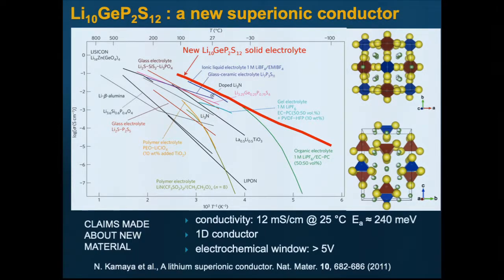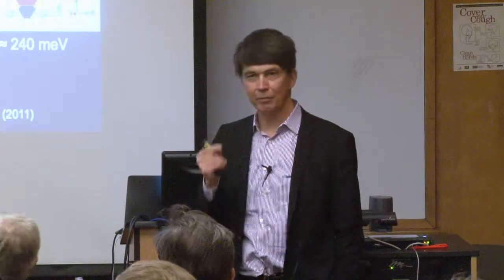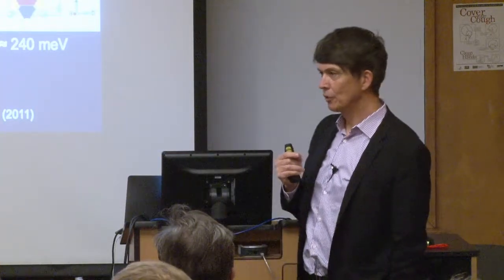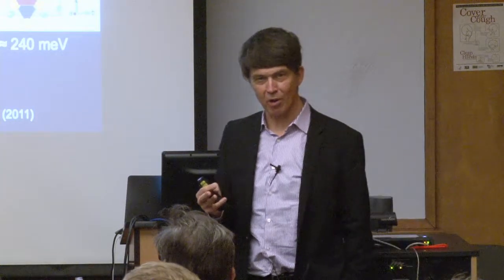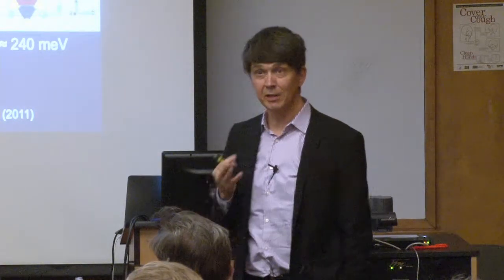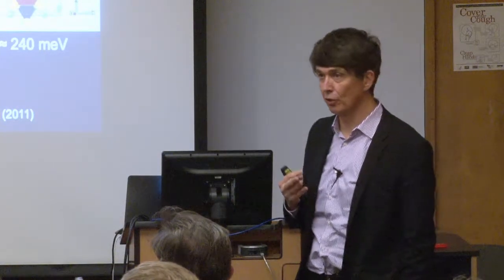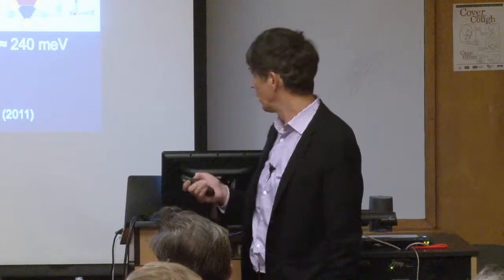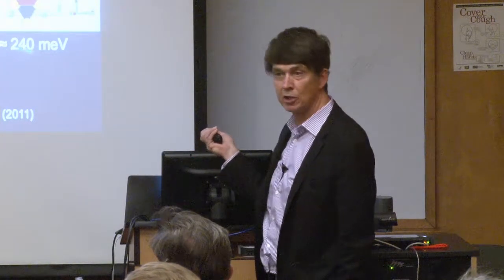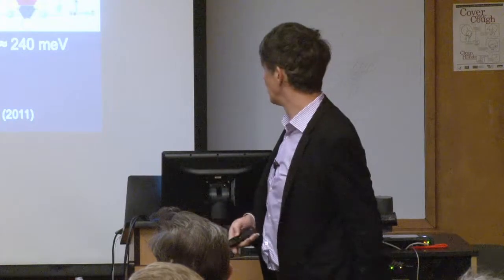Now, they claimed very high conductivity, 12 millisiemens per centimeter, which is exactly where organic solvents sit. They claimed it was a one-dimensional conductor, with a super high electrochemical window of stability over 5 volts. The interesting thing about this paper is that it's almost completely wrong, except for the important thing, the conductivity. So almost everything in this paper has been proven wrong, but fortunately, the material indeed has super high conductivity, and it's sort of remarkable, right? This is a remarkably low activation energy for motion of ions through a solid.